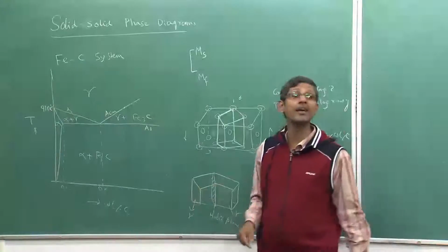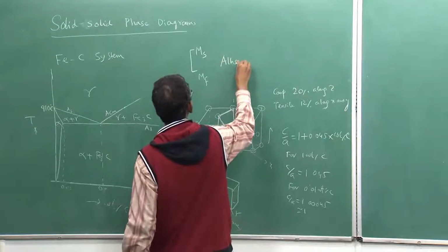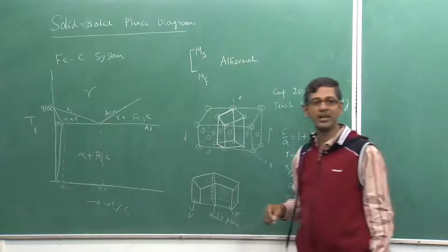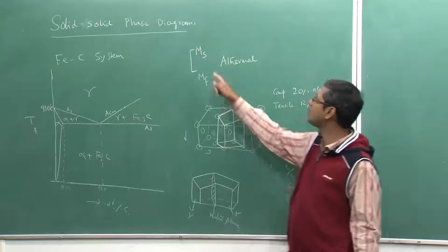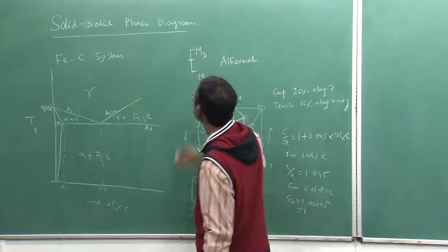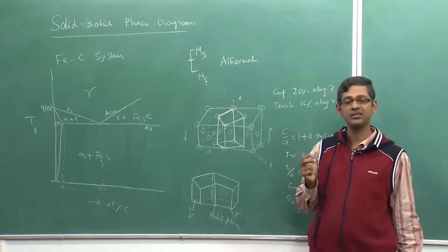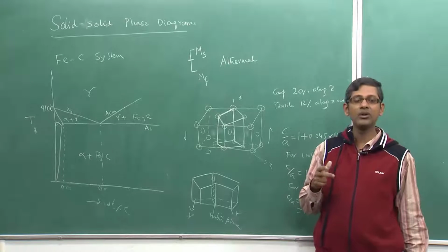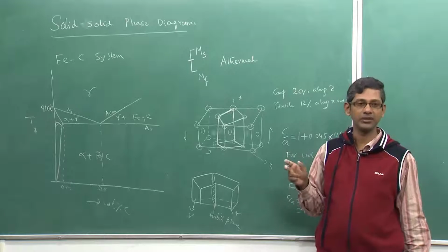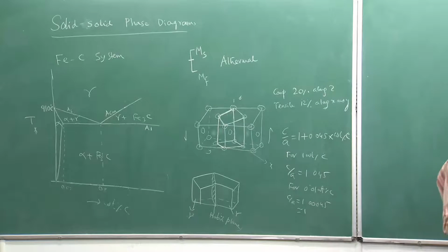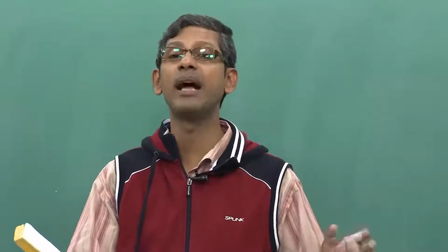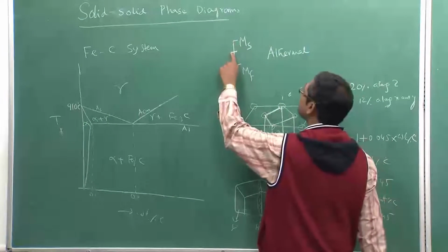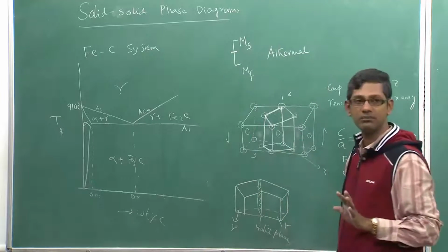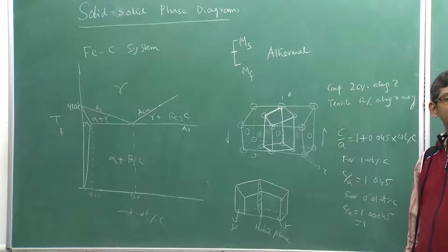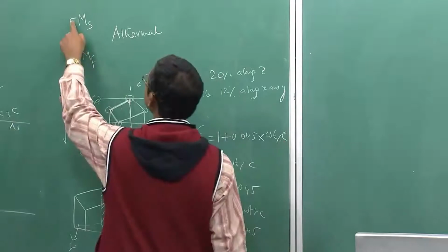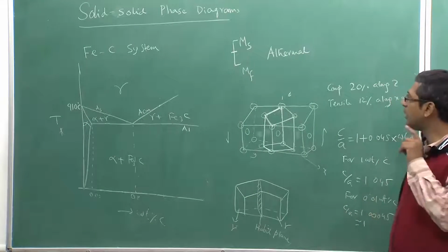Second important thing, this transformation is athermal in nature. These are the terms you will hear in steel metallurgy. What does that mean? That means if I cool the sample below MS, transformation will happen spontaneously, but it will not depend on any further decrease or cooling rate. That is what is known as athermal. Or rather I can tell you in a very nice way, this transformation is basically independent of time. Unlike the pearlite transformation, which depends on time, that is a rate, here it depends on the temperature below MS, that is all. If you cool it down below MS, it will transform.